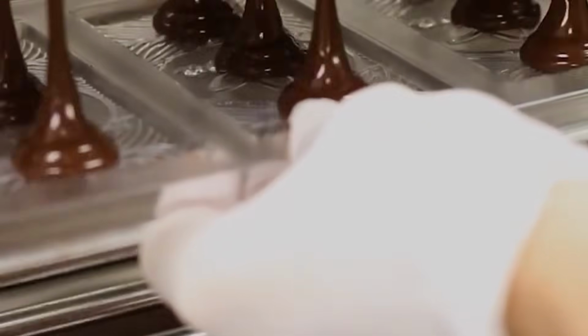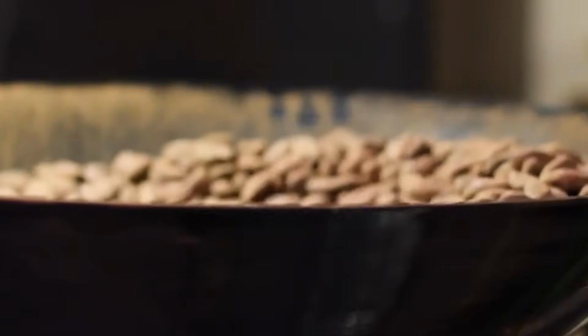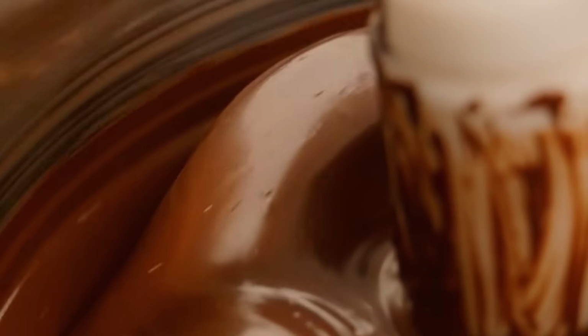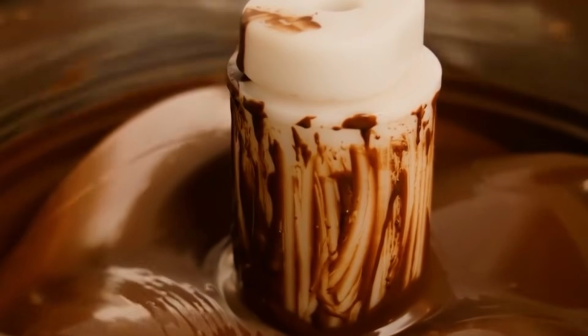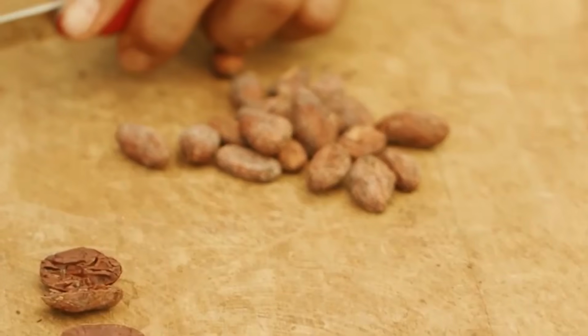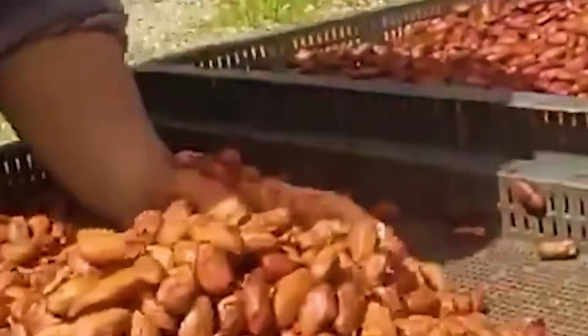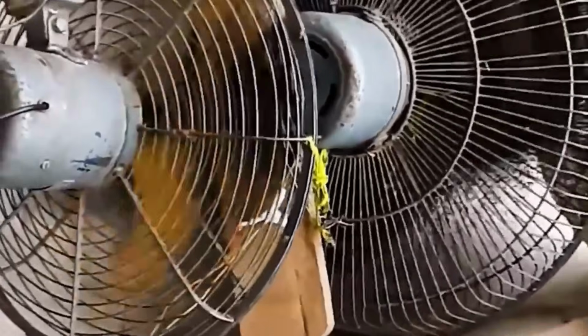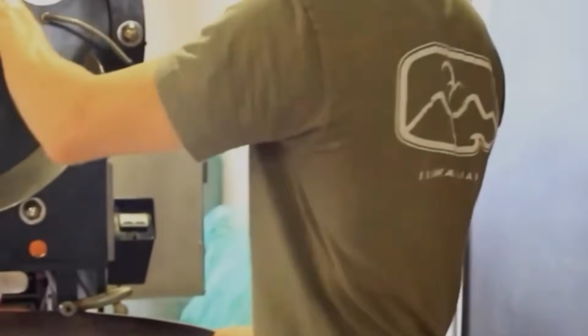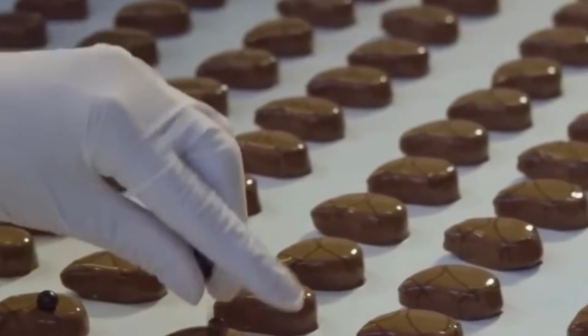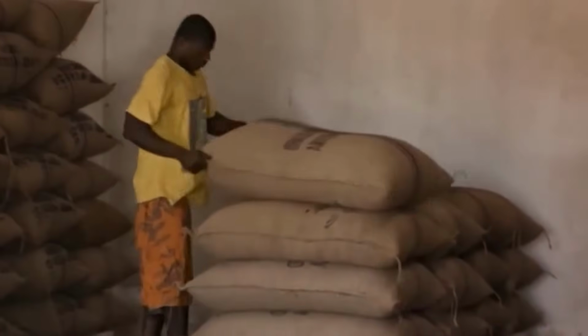The temperature and duration of roasting are carefully controlled depending on the variety and origin of the bean, and are adjusted based on moisture content and desired flavor profile. Once roasted, the beans are cooled rapidly using forced air to prevent over-roasting, and then they move to the winnowing machine. The winnowing process cracks each roasted bean and separates the outer shell from the nibs inside. This is done using mechanical rollers that crush the beans gently, and blowers that blow away the lighter shells while heavier nibs fall into collection bins.